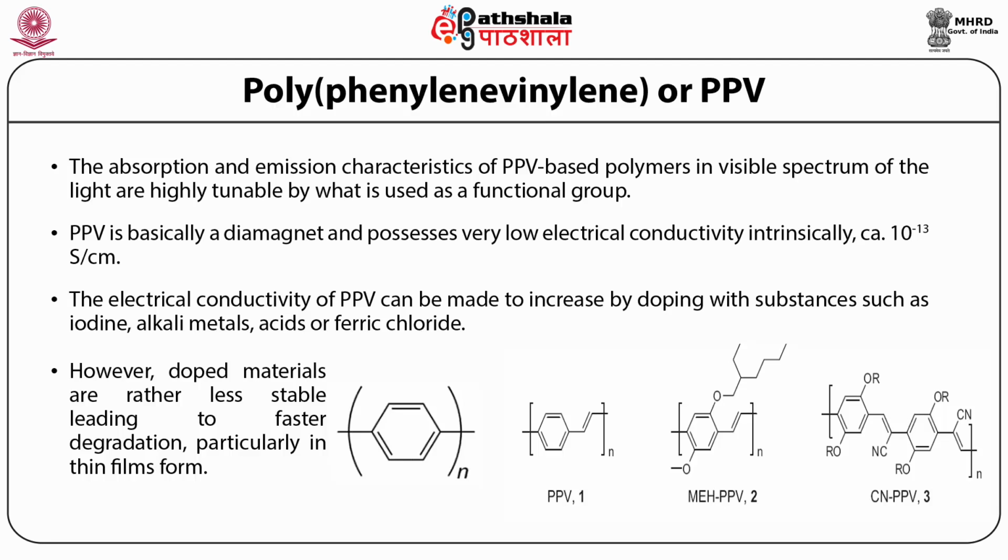Higher conductivities can be expected in the alkoxy-substituted PPVs, which are generally easier to oxidize than the parent PPV. The longer the side chains are, the lower the conductivity, since it is very difficult for charge carriers to hop between chains. PPV is the only polymer of the rigid rod family that can be processed into a highly ordered crystalline thin film.